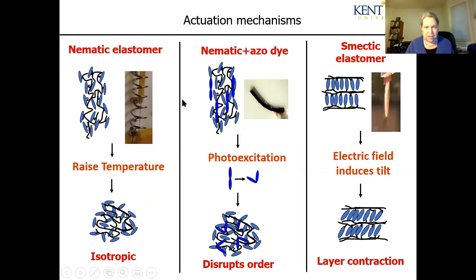So just for these particular examples, what's going on? In the case of the nematic, when you raise the temperature, it might go full isotropic, or it might just have reduced nematic order, and this causes it to shrink. So this is supposed to be a cartoon representation of the polymer. We have here a polymer backbone, and here the little mesogens that are rod-shaped liquid crystal type molecules are dangling off the main chain. They could also be in the main chain. They could be tethered side on or edge on. All those details of polymer physics are interesting and change the material properties. But the key issue is that when the molecules undergo a change in their orientational order, the material actuates. And it typically actuates by shrinking along the axis of nematic order and growing a little bit in the other two directions.